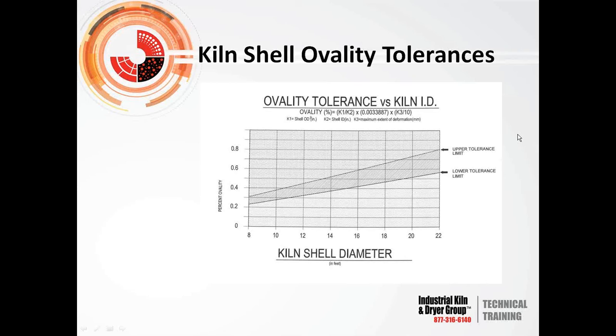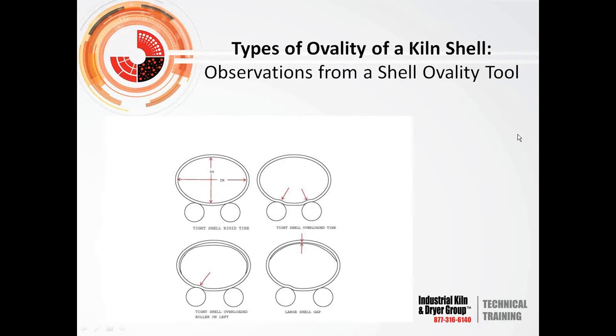And when Holderbank originally designed this thing, from what I understand, Roland, they used some empirical data to determine what percentage of ovality was acceptable per the diameter of shell. So there's a lot of charts to compare this to, so that you know that your tire's in the range that it should be. Yeah, and on kilns, it's critical with regards to refractory failure, and that probably is the one item that determines what the percent ovality is acceptable.